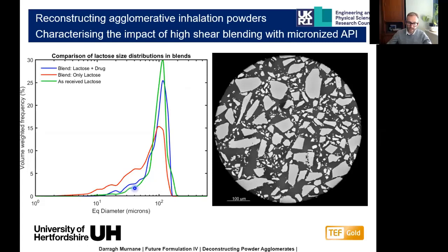So this green line here is as received. We can see that by undertaking high shear blending on the lactose without any drug included in the system, we've ended up actually creating some intrinsic fines within the blend that weren't there to start with, so the high shear energy has done that. However, when we formulate with drug, we can see that that creation of fines doesn't occur.